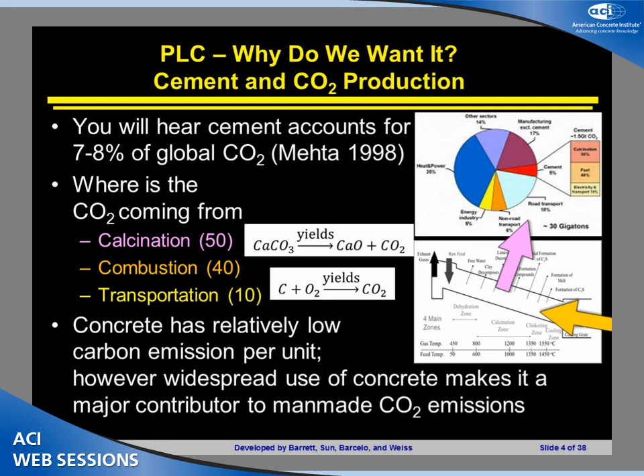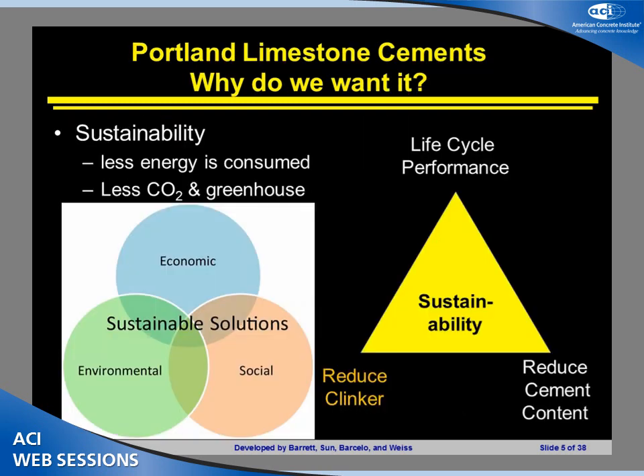About 50% of that CO2 is coming from the calcination process, 40% is coming from the combustion process, and 10% from transportation. If we can replace some of that clinker, we can really act to reduce some of the CO2 coming from calcination, some of the CO2 coming from combustion, and substantially reduce the CO2 that's being produced with that concrete. So the real big takeaway on why we want it is, again, the sustainability issue.